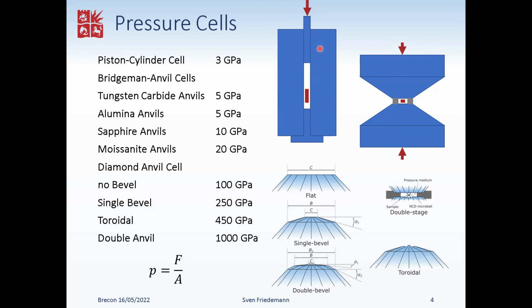Maximum pressure that is frequently generated for condensed matter research for quantum materials or so is of the order of 3 GPa. Beyond that, one would have to have enormously thick cylinders, and then one can't stick it into a cryostat anymore, and so on. So that's why 3 GPa is pretty much the practical limit for piston cylinder cell work.